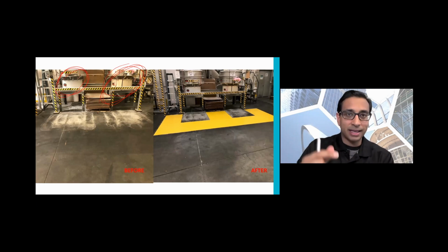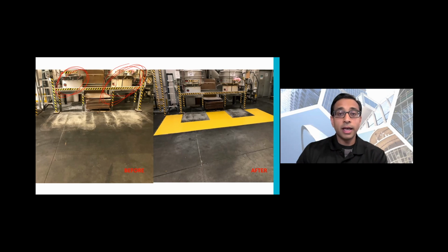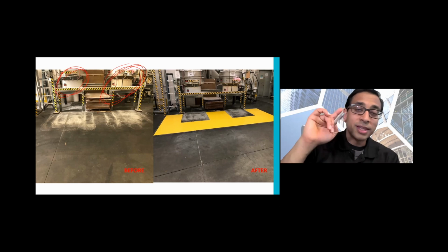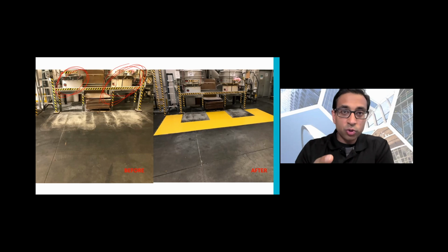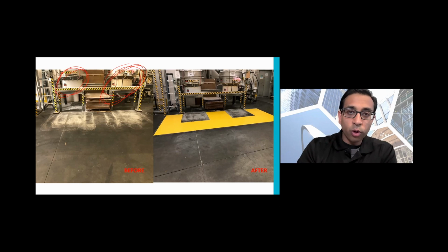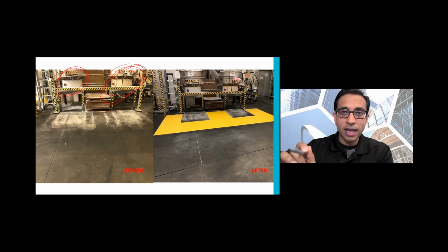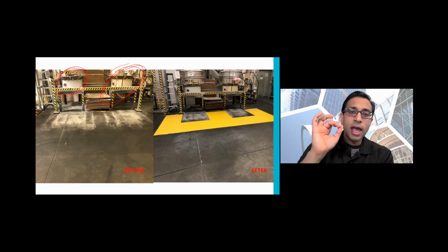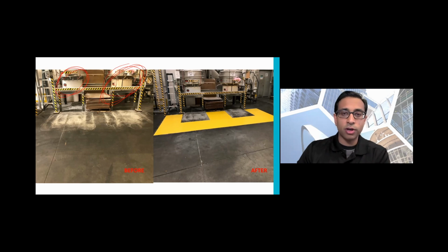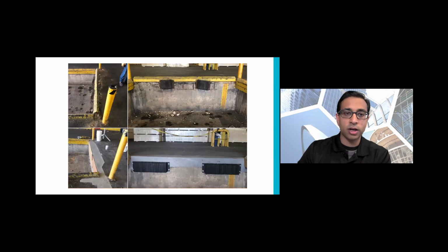And they're tiny. So when they get dumped out, if any of them get on this very smooth concrete, guess what? It's like stepping on ball bearings on smooth concrete. It's very, very bad. It's not very safe at all. So the same approach was used. The floor was prepared, an epoxy was put down, an aggregate thrown in the epoxy, and then that beautiful safety yellow put on there. Now, an anti-slip situation has been created, a much safer work environment for the workers there.